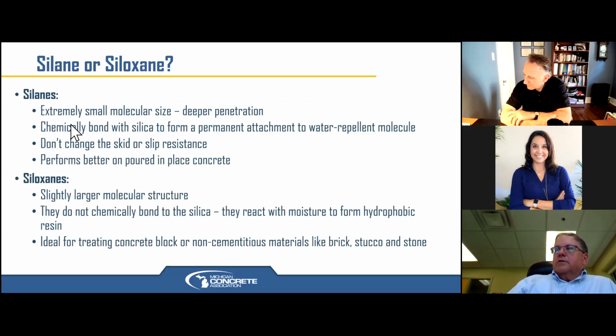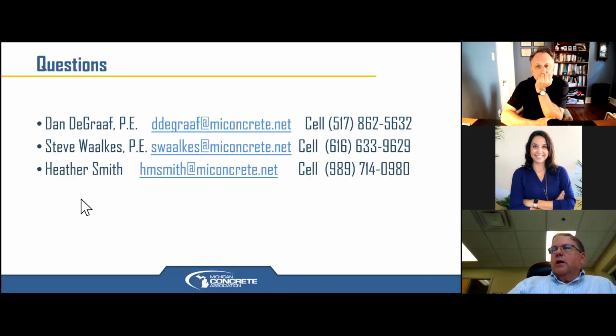So silanes are extremely small. It penetrates the surface, so you spray a silane down and it'll look like it didn't do anything. But it soaks right into that concrete and reacts internally. It doesn't change your skid or slip resistance, and it really works better for a direct application on concrete. Siloxanes are slightly larger. They do form a hydrophobic resin, but they're really great for concrete block and non-cementitious material like brick, stucco, exterior or vertical walls. But silanes are really something we need to think about, at least before that first winter. By the time the second winter rolls around, our SCMs have reacted, and we have a nice, very dense mix that will perform well.